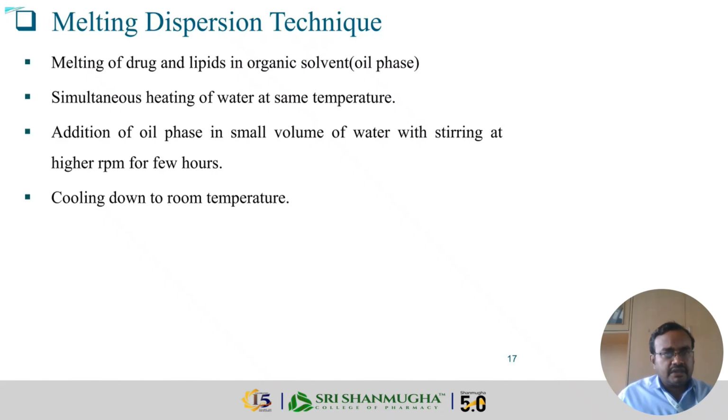Then the melting dispersion technique. In this technique, the drug is melted with the lipid in an organic, oily phase, while water is simultaneously heated to the same temperature. The oil phase is added to a small amount of water with continuous stirring at high RPM for a few hours. Then it is cooled down to room temperature.